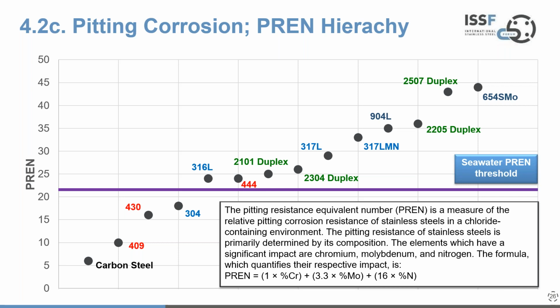So now I'd like to look momentarily at the pitting resistance equivalent number. And we have here a range of primarily stainless grades, but right at the bottom left, carbon steel. And each of these products is shown where its position is on the pitting resistance equivalent number scale, which is the left-hand y-axis. There's a horizontal line on there, which is the threshold for corrosion resistance in seawater environments. So you can see in this, there are some stainless steels that are not so effective if operating in a seawater environment, and carbon steel certainly isn't. And you can see there the expression for how this pitting resistance equivalent number is built up. So this is a useful guide, and in one of the appendices documents, there is further guidance on how to use this to good effect. But this just illustrates the range of pitting resistance equivalent numbers we have across the bulk of the stainless family.